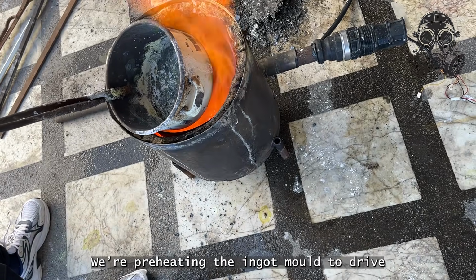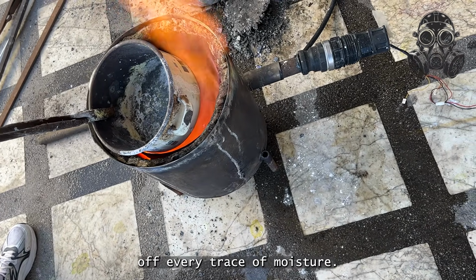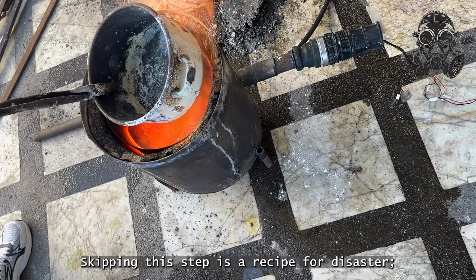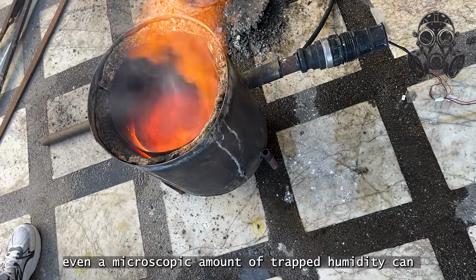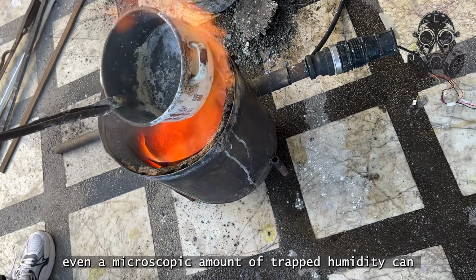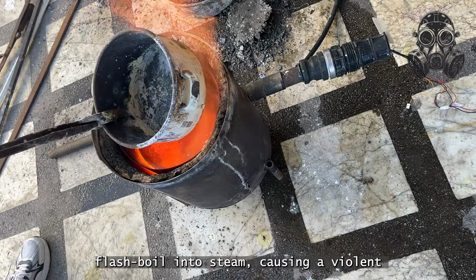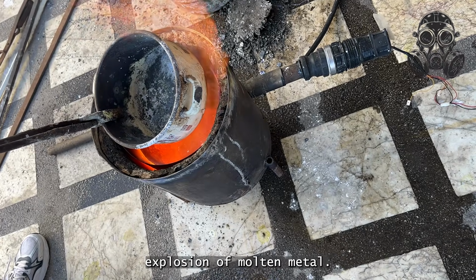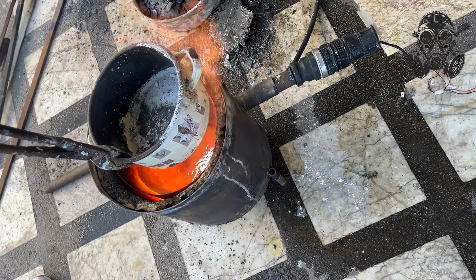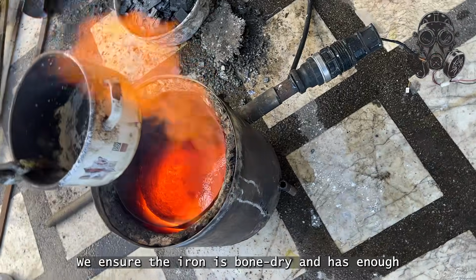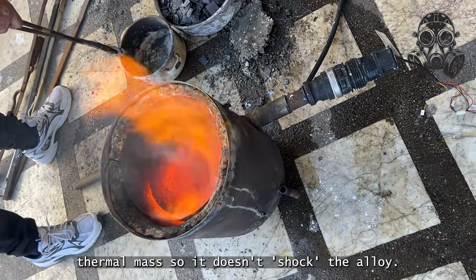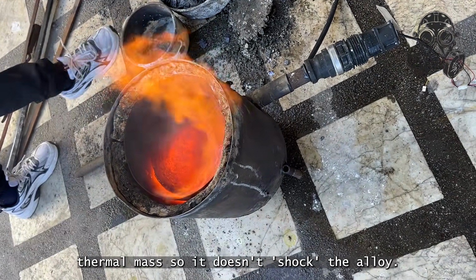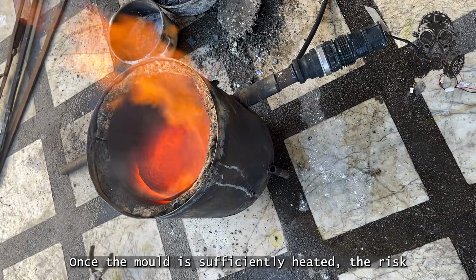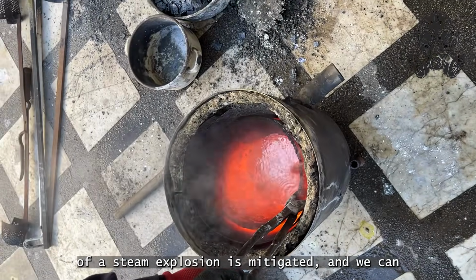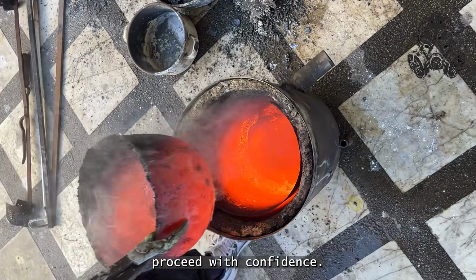We're preheating the ingot mold to drive off every trace of moisture. Skipping this step is a recipe for disaster. Even a microscopic amount of trapped humidity can flash boil into steam, causing a violent explosion of molten metal. We ensure the iron is bone dry and has enough thermal mass so it doesn't shock the alloy. Once the mold is sufficiently heated, the risk of a steam explosion is mitigated, and we can proceed with confidence.